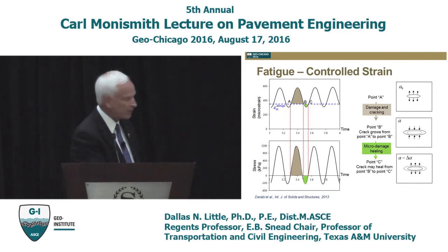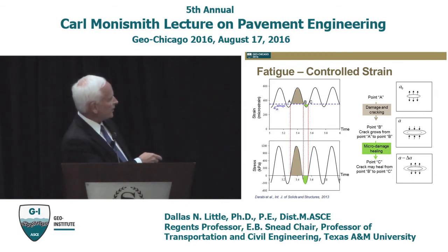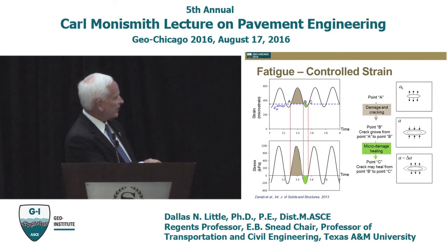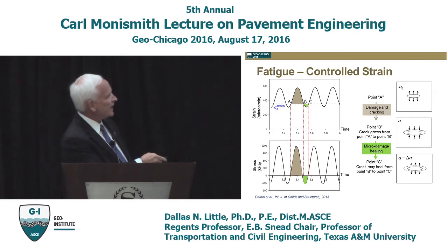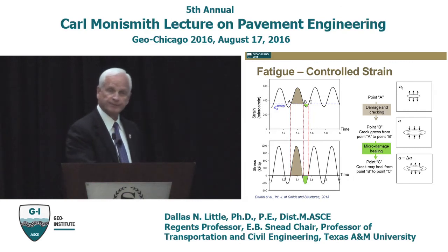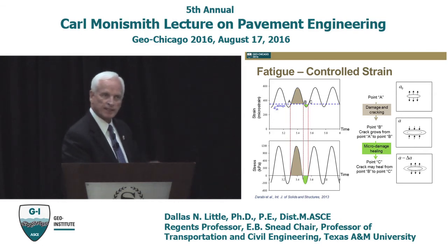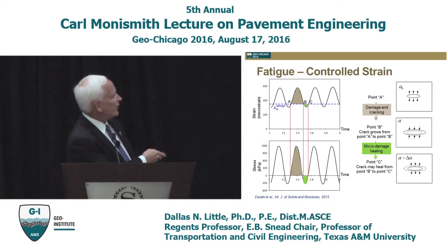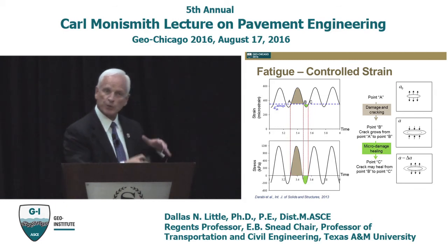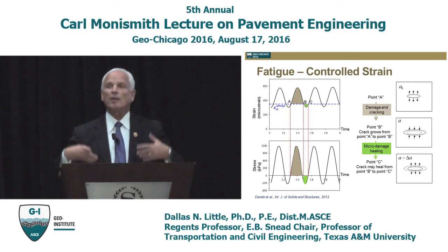This is a uniaxial sample. So we're going to pull a strain on it, we're going to push it back together, and during this tensile mode from A to B, of course we have a tensile stress, and when we go from A to B, the crack is becoming longer. Fatigue damage is occurring because of increasing microcrack length. When we put the compressive mode into play from B to C, we develop a compressive stress in that controlled strain sample as we push it back together. And one would think that during that compressive mode, maybe some of that crack that's pushed back together would re-wet, reorganize, and you'd develop at least a partial recovery in strength.